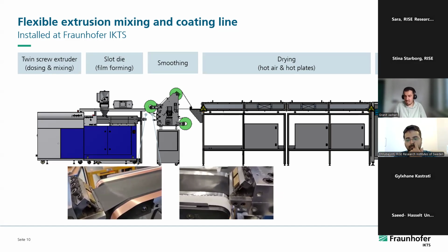The slot die that we are using has a 100 millimeter width. We also have 150. The slot die geometry is one of the key points in order to achieve a really flat film and also to make this direct extrusion of the material onto the current collector. On the bottom, you can see pictures of how that looks for the anode and the cathode, directly coating the film onto the current collector.